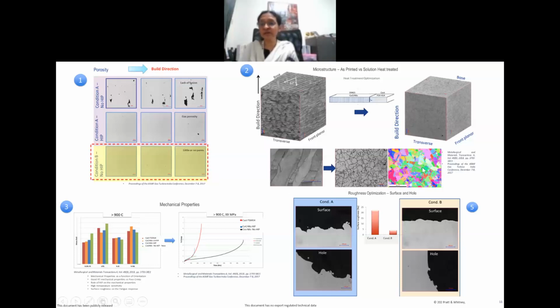So we converted it into this. This is an EBSD pattern which shows no orientation dependence, as demanded by this application in the power nozzle, which was going to operate at high temperatures. And we also had a recrystallized microstructure, which is fine grained. Now, when our chief engineer saw this, they said, absolutely a no-no, Deepa, because you're going from a casting microstructure with large grain size, and you're going to have a 30 to 40 micron grain size out here. Absolutely no for this high temperature application, because fine grained microstructure is very bad for creep. So what I'm pointing out to you is challenge number 2, of how you need to intelligently overcome this.